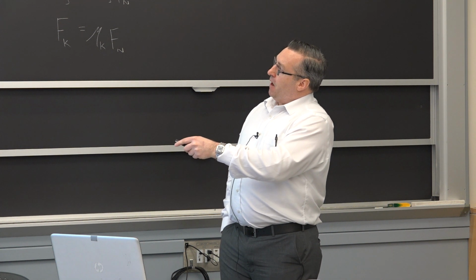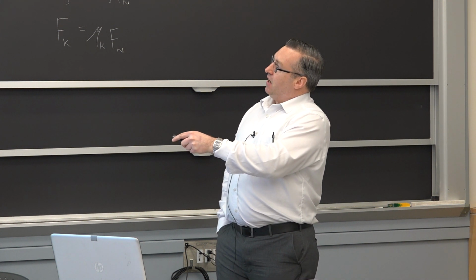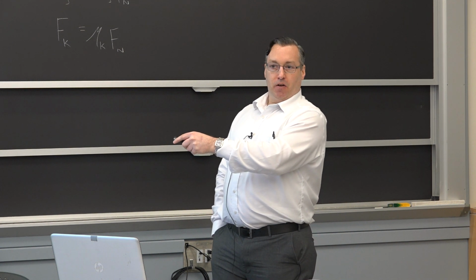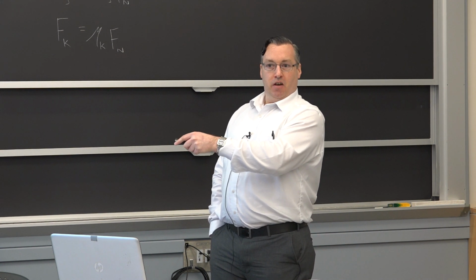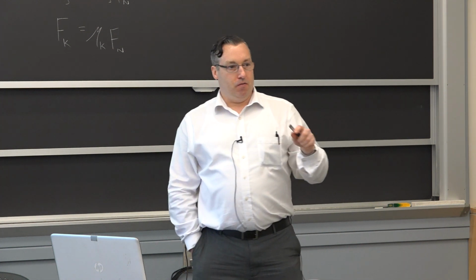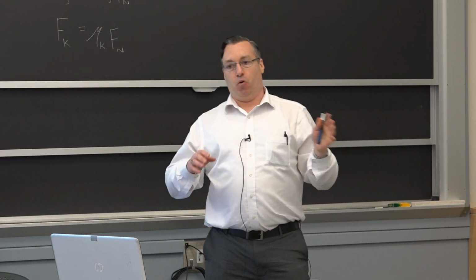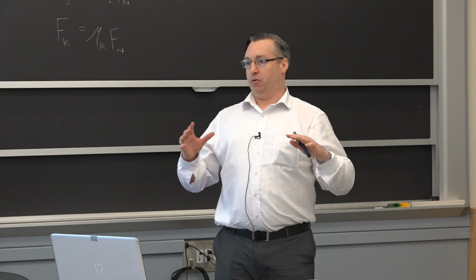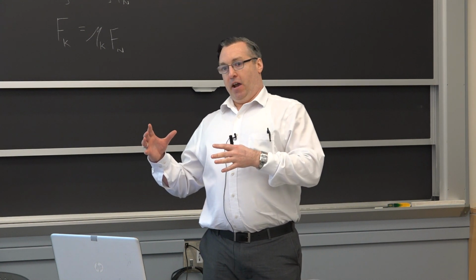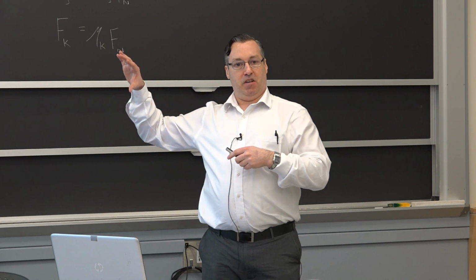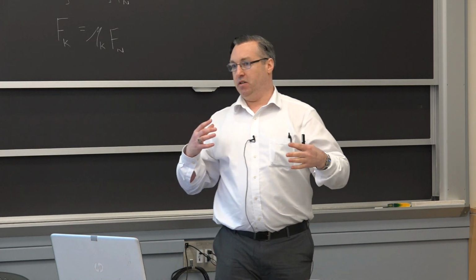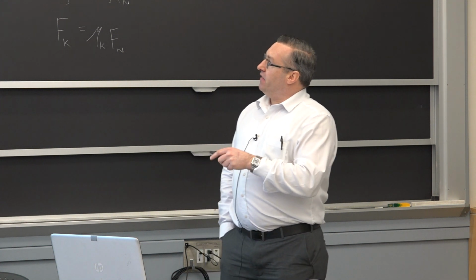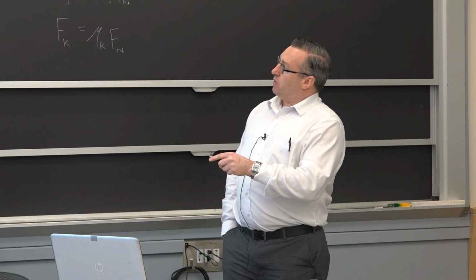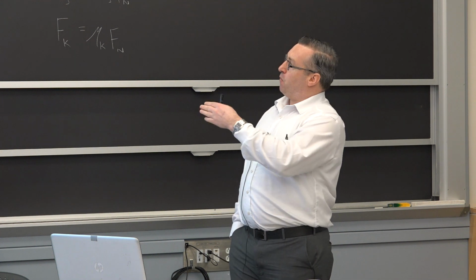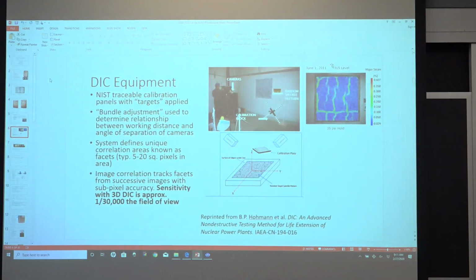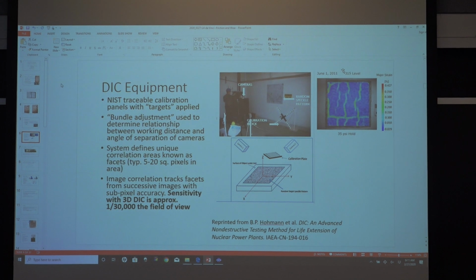This is your random speckle pattern here, and this is actually a wall on the containment of an operating nuclear plant in the US. In order to prove to the NRC, the Nuclear Regulatory Commission, that there was no degradation inside the containment that you couldn't access with a human, they allowed us to go in there and set up this speckle pattern, and we performed the digital image correlation while the nuclear plant did what's known as a structural integrity test.